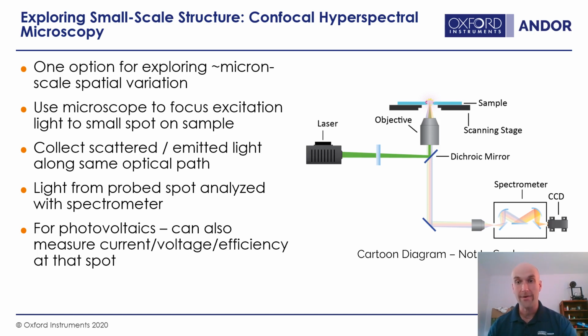So we're going to use a microscope to focus the excitation light on a small sample, diffraction limited if we're doing really well. And we're going to collect that light that comes from that sample, both scattering and emission, along the same optical path as we use for excitation. And our light from the probe spot will go through the microscope out to a spectrometer and get collected and recorded by a CCD. So for photovoltaics and other optoelectronic things, we can also measure current, voltage, and power conversion efficiency at that spot, which is really important because of the amount of variation both in the chemistry and in the packing and so on, and how that affects the actual device efficiency.